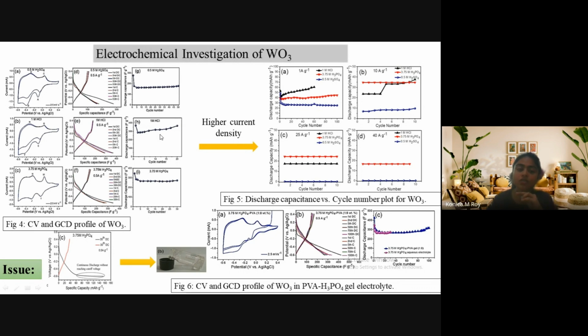So it is leading to HER, hydrogen evolution reaction. To suppress that, we have chosen one strategy and moved forward with H3PO4, because at higher current density we could see that H3PO4 shows a better result at a very high current density of 40 ampere per gram. So we have prepared a specific kind of gel electrolyte using PVA, polyvinyl alcohol, because it has very high conductivity as compared to other polymers.